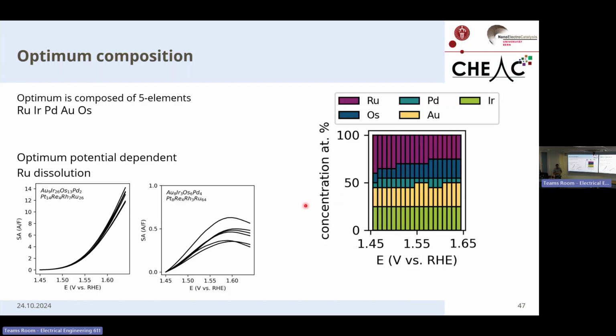Ruthenium is a very active catalyst for the oxygen evolution reaction, but incredibly unstable in acid. So ruthenium-rich samples tend to show these peaks due to the decay of the catalyst. Whereas if you have a moderate amount of ruthenium, you have this exponential increase.